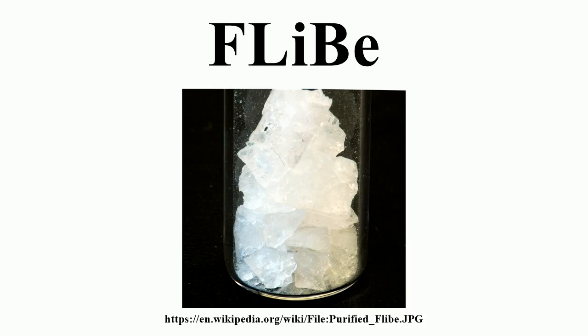The eutectic mixture is slightly greater than 50% BeF2 and has a melting point of 360 degrees Celsius. This mixture was never used in practice due to the overwhelming increase in viscosity caused by the BeF2 addition in the eutectic mixture. BeF2, which behaves as a glass, is only fluid in salt mixtures containing enough molar percent of